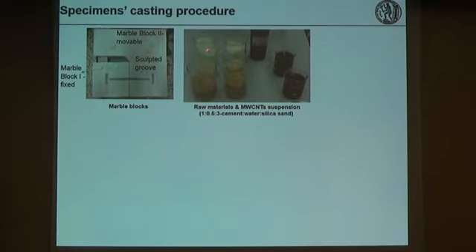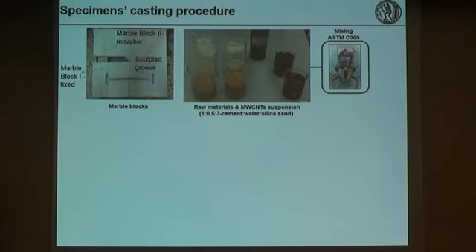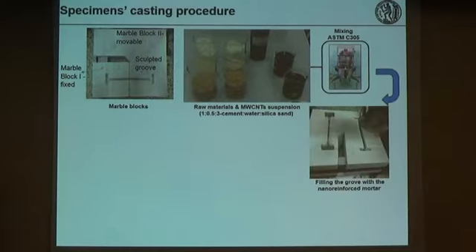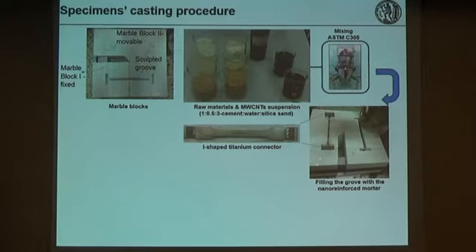And what I want to point out is that these materials, the matrix, the raw materials, and the mixing, were based on the material that's currently being used at the restoration of the Parthenon. So we mixed the materials using the standard. We filled the groove with the nano-reinforced mortar, and then we placed inside the I-shaped titanium connector.